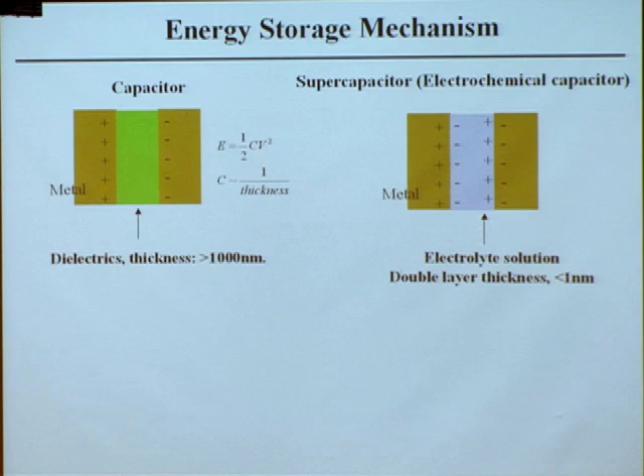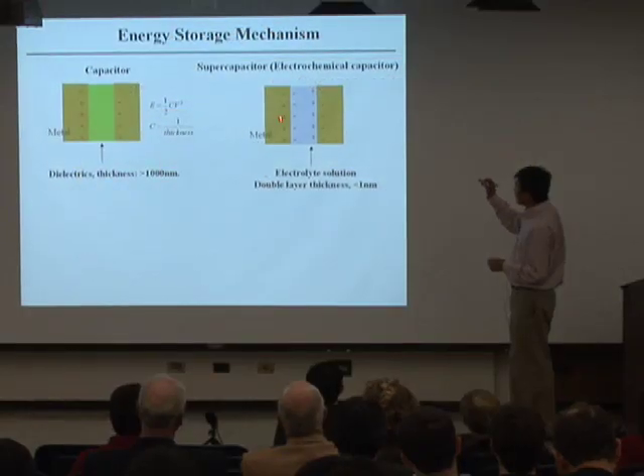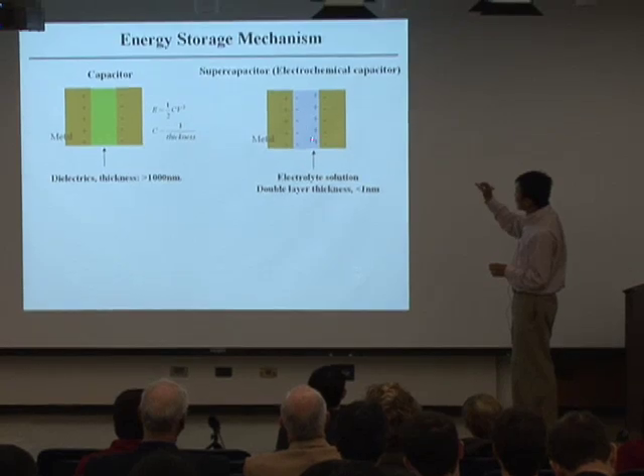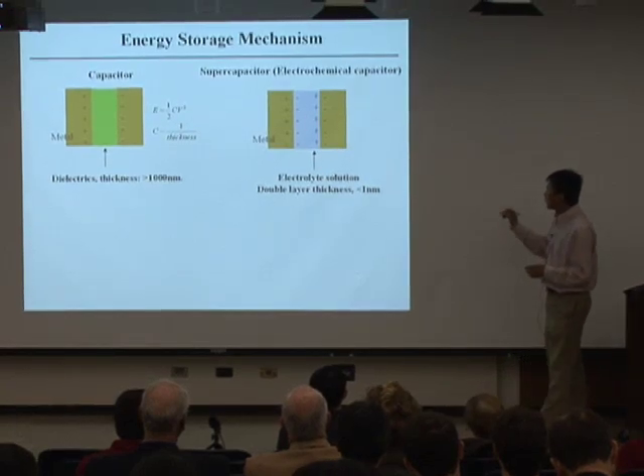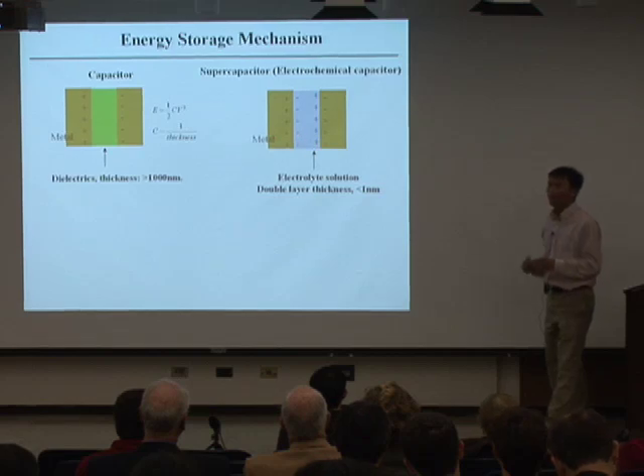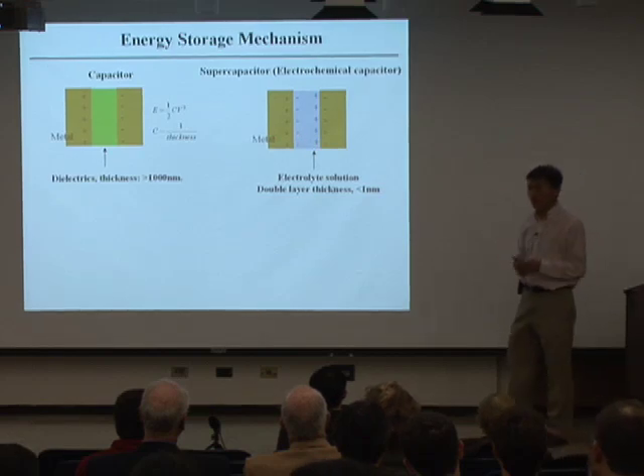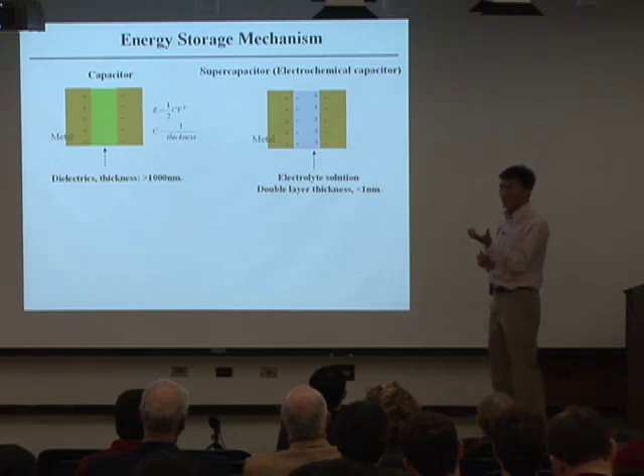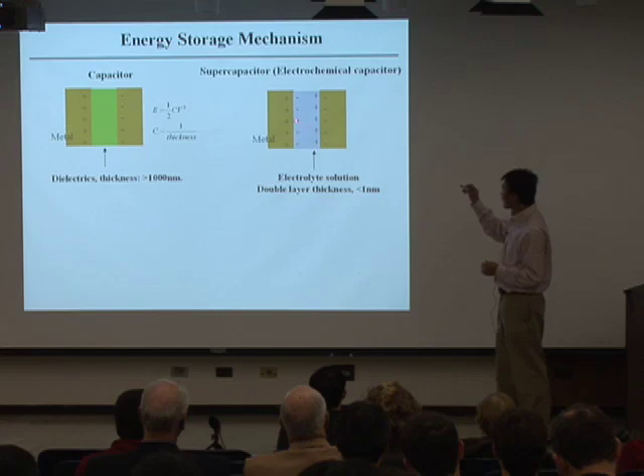Supercapacitors, or say electrochemical capacitors, use different mechanisms to store energy, slightly different, but more or less similar to capacitors. So the idea is, how do you reduce this dielectric thickness down to nanometer scale, about 1,000 times smaller? The idea is you take these two pieces of metals, instead of using dielectrics, now you use electrolyte solution. So it's in, for example, aqueous solution. You have salt dissolved in the aqueous solution, so you have ions in the solution.